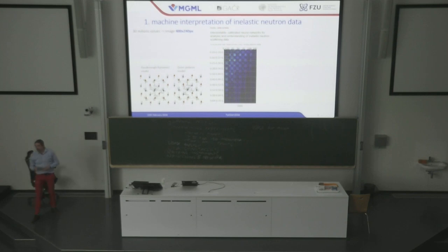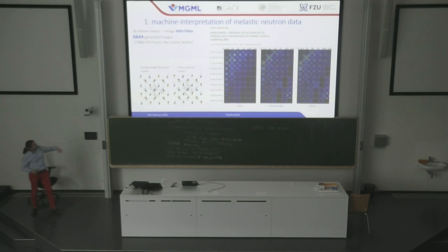Maybe it will be more clear. The method is time of flight neutron scattering. The point is that we are tackling which excitations, at a particular momentum transfer in the system, can contribute at which energies to our final spectra. So this is basically telling us about the phonon vibrations, the magnon vibrations in the system, and basically anything which is possible to excite in the system.